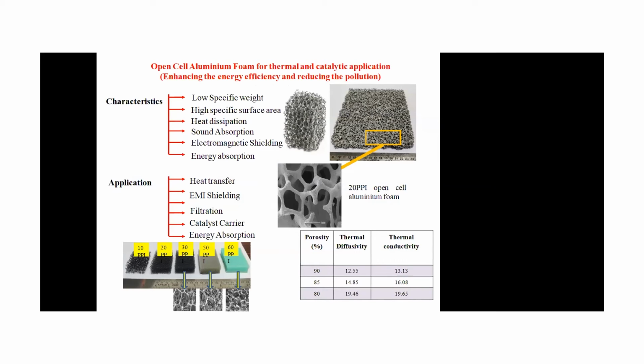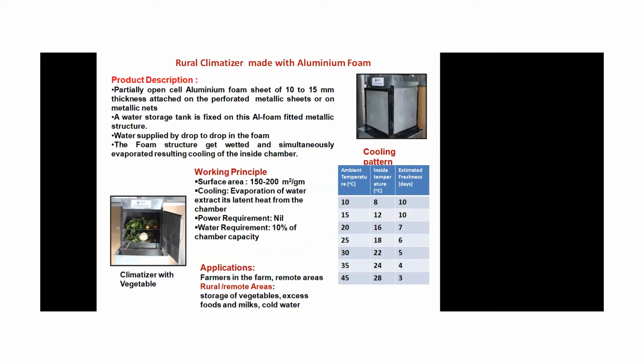So there we are not measuring any strength part, but we have to be concerned about the surface area and the thermal conductivity part. You can see this thermal conductivity is very high, so we can use it for heat transfer as well as EMI shielding application. The same thing we have made for the cooler, so we can make the same kind of cooler using open cell foam because the heat transfer rate is very high.